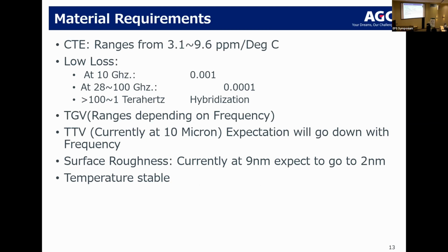So, what's needed for glass? CTE is probably one of the most important things, especially if you use it as a carrier or if you use it as glass core. So you've got to match the silicon CTE, because if you don't, then you get stress in the package, and then it actually reduces the reliability. At 10 gigahertz, 28 to 100, and 100 to 1 terahertz, the loss of the glass is important for most